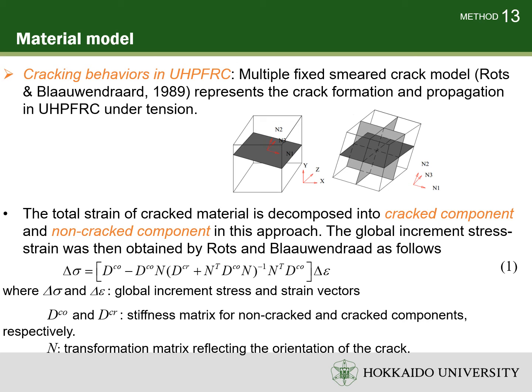The total strain of cracking material is decomposed into crack component and non-crack component in this approach. The global incremental stress and strain were then obtained by Rots and Blaauwendraad as follows, where delta sigma and delta epsilon are the global incremental stress and strain vector. DCO and DCR are the stiffness matrix for the non-crack and crack component. N is the transformation matrix reflecting the orientation of the crack.